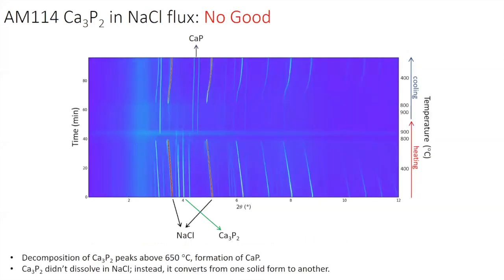In contrast, if we consider sodium chloride, this turns out not to be any good. These again are the flux peaks, these red ones. And as we go into the melt here, you see that what we started with, which was calcium 3 phosphorus 2, actually turns into a new compound, calcium phosphide. So that showed us right away that sodium chloride flux would never work. It would yield the wrong compound. So that's just a quick example.